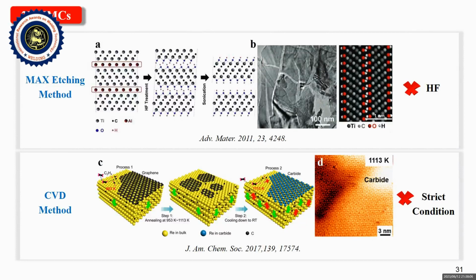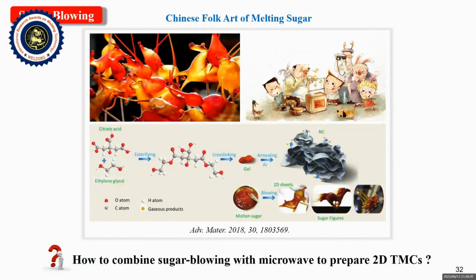In addition to zero-dimensional carbides, two-dimensional carbides with high specific surface area can also show excellent kinetic activity. However, the MAX etching method requires dangerous acid, and the CVD method faces stricter conditions. But in China, there is a folk art of melting sugar by heating and blowing it to get different interesting shapes. So we thought about how to combine sugar blowing with microwave to prepare two-dimensional transition metal carbides.